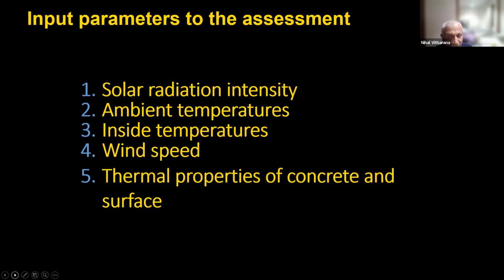Then thermal properties, concrete and surface absorptivity. Because if it is a dark surface, black, the absorption coefficient is about 0.9. If it is white, it's 0.35. So if you can afford to paint the walls in white color, or use reflective sheets, it will set the temperature gradient lower. Such things have been done in the past and even nowadays, but it's a very costly exercise.